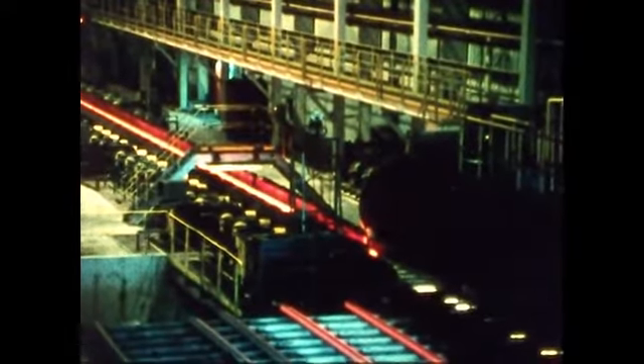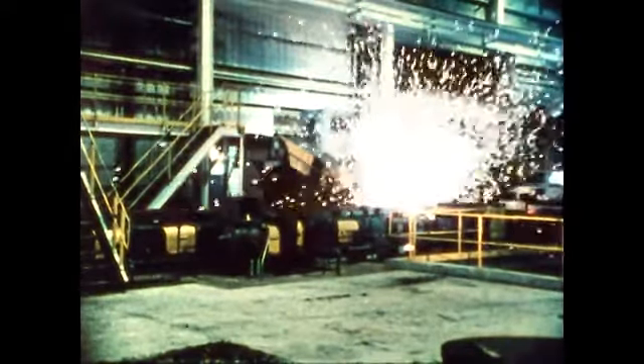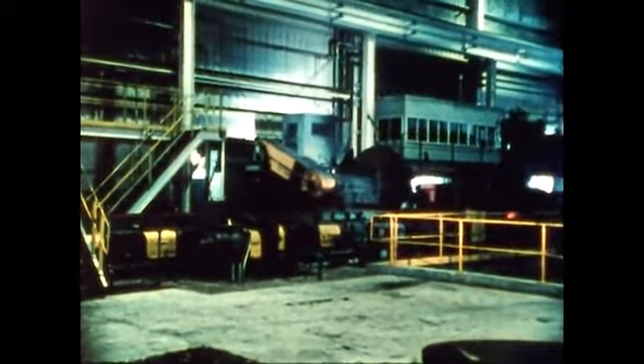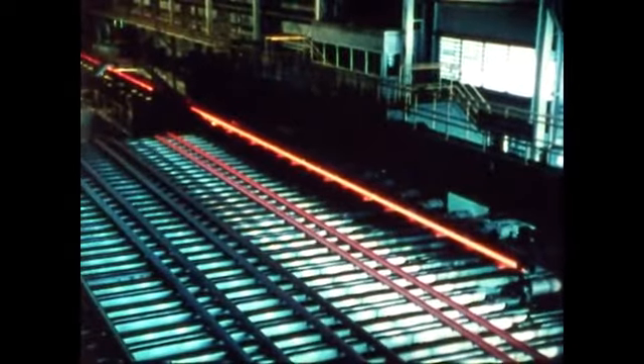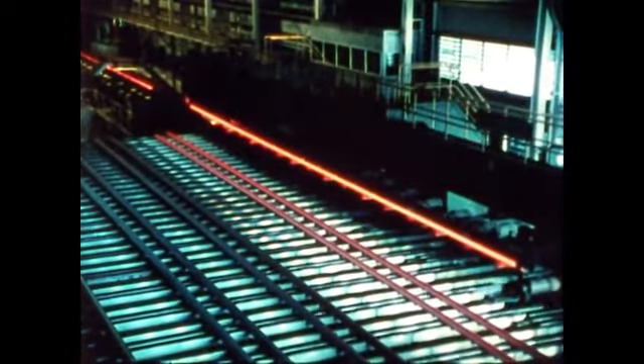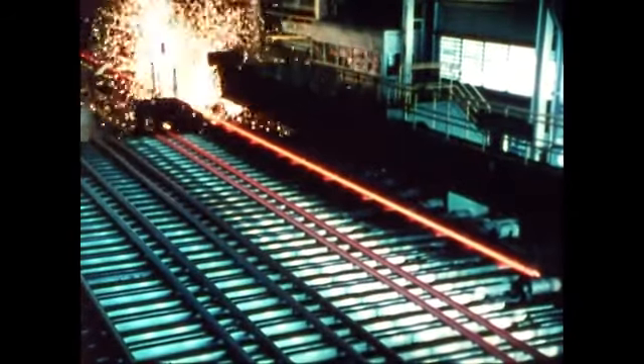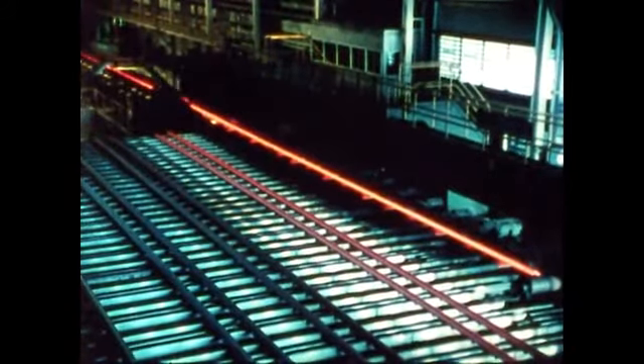It is at the hot saw where samples are taken for a variety of quality control checks on dimensions, symmetry, surface, internal structure, hardness, and ductility. Then the rail is cut into 2 lengths, each over 80 feet long, and moved to this sophisticated cooling bed for precise cooling to meet mechanical requirements. Walking beams, fully adjustable for speed and stroke, ensure that rails are never exposed to mechanical damage.